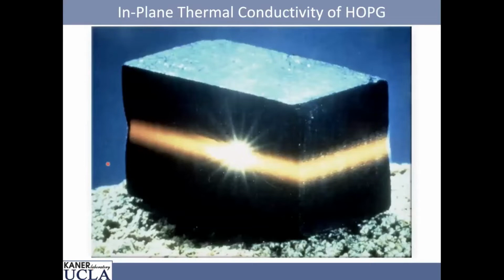This is my favorite picture of pyrolytic graphite. This is a piece about the size of your thumb, and it's from Neil Bartlett's lab, where I did my postdoctoral work in the mid-1980s. What we're doing here is hitting this block of graphite with a laser. Now, a normal material would heat up in 3 dimensions, but graphite certainly is not a normal material. As we probably well know, heat conducts by 2 different mechanisms. One is phonon modes, in other words, the chemical bonds.